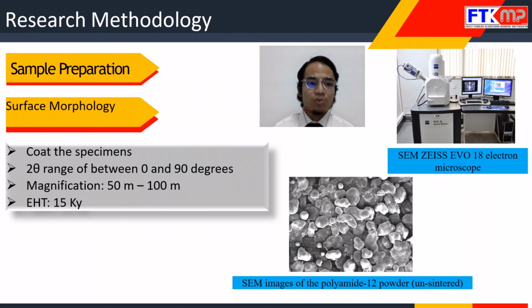The next test will be surface morphology. Before I run this test, I have to coat the specimen first and set the range between 0 to 90 degrees, and set the magnification for 50 micro and 100 micro, and the EHT value is 15 kV. This is the testing machine that will be used, the SEM ZEISS EVO electron microscope, and the pictures below describe an example of the SEM image that I will get.